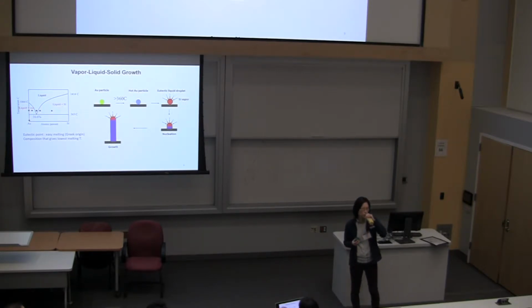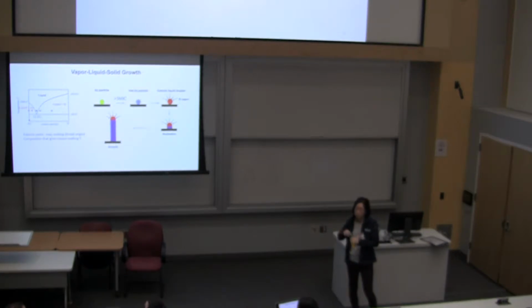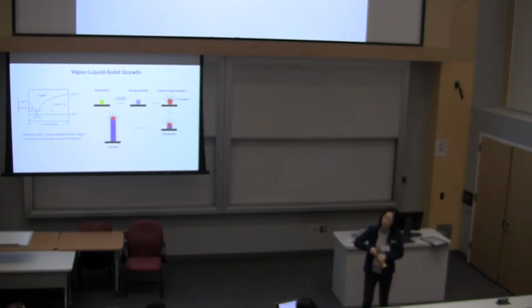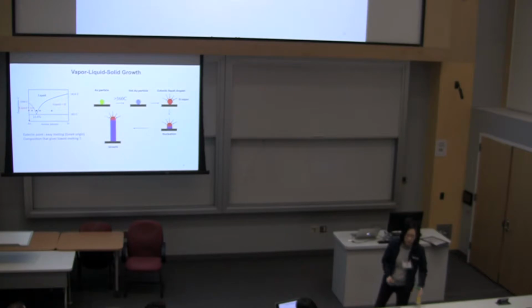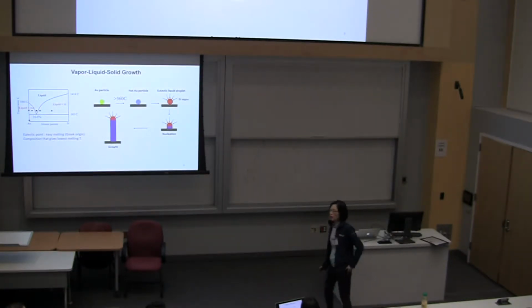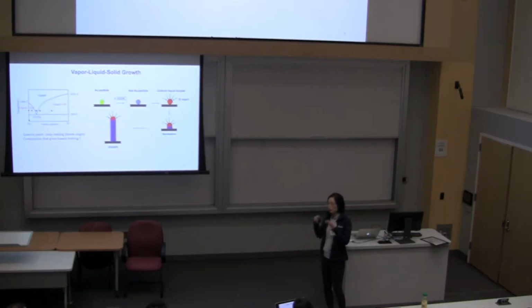Okay. I have a question. How much gold actually is left over in the silicon wire? Is there any at all? There are gold atoms in it. I don't think I have a quantitative number that I can say, but people have done high resolution STEM scanning TEM work and shown gold particles embedded.